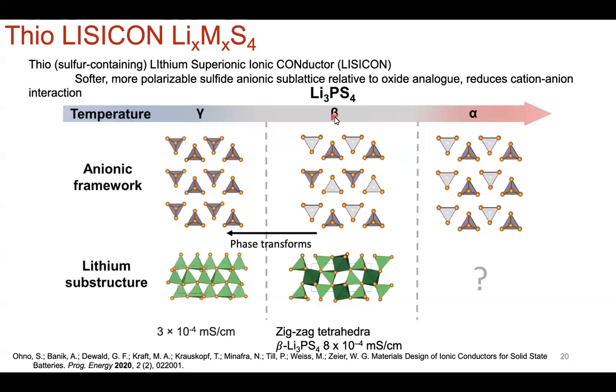So those are three great starting strategies to access these phases that are typically inaccessible. You could really think about so many ways of agitating and perturbing the system to access even metastable phases. You mentioned quenching, which is reduction in temperature at a very fast rate, right? And that's how bulk metallic glasses are made. You get your cocktail of compositions, 10, 15 elements, metals, into a molten state, and then you quench at 1,000 Kelvin a second or a few seconds, and that's how you get bulk metallic glass structure. So quenching is definitely a way to access these high energy phases.